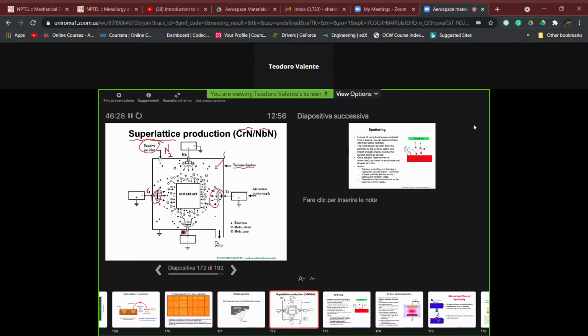And if, for example, we rotate this substrate with a selected choice, we can have the fabrication of a first layer of chromium nitride. Then we can have the fabrication on this other surface of niobium nitride, etc., giving rise to multi-layered coatings. They are called superlattice in the case in which, and this is the case, the thickness of the single layer is around, as we said before, 10 or something a little bit higher nanometers. Thus reaching the final coated thickness by having a layered structure inside the coatings, in which each layer has a thickness of the order of 10 or something more, I repeat, nanometers.